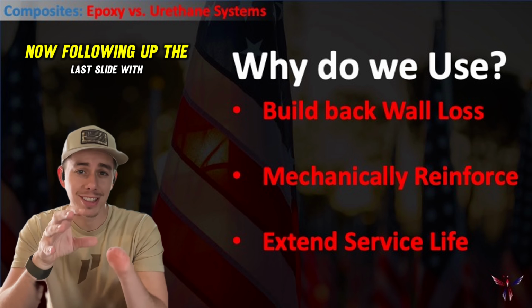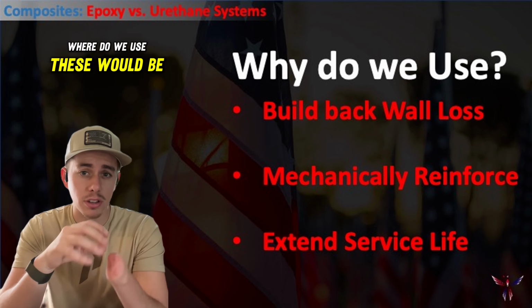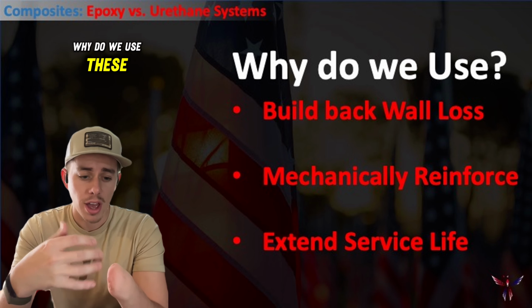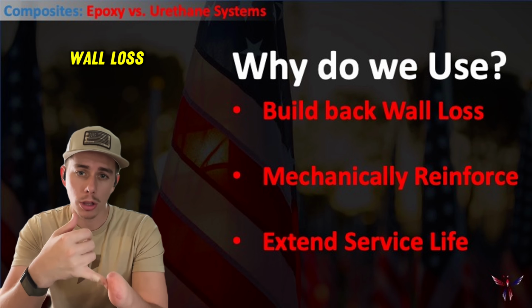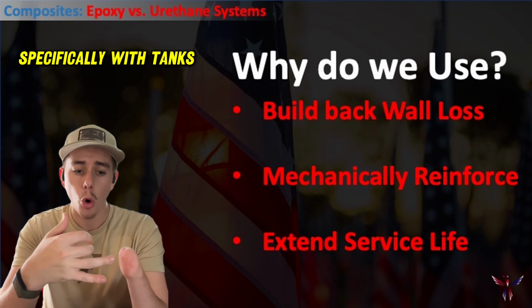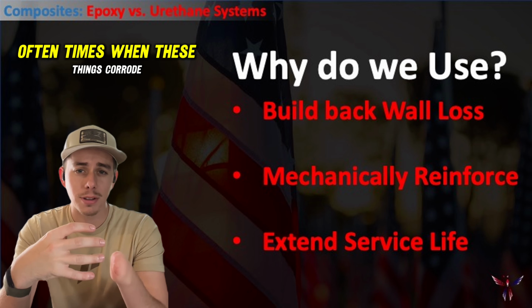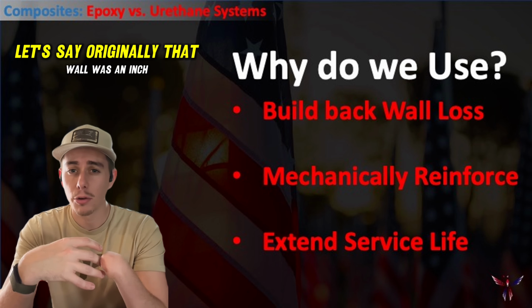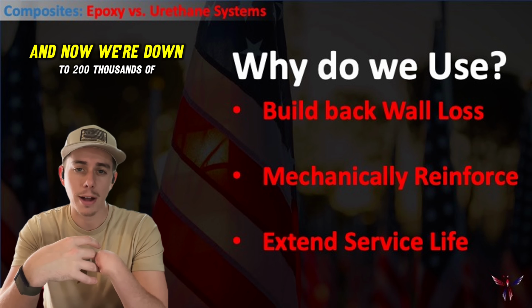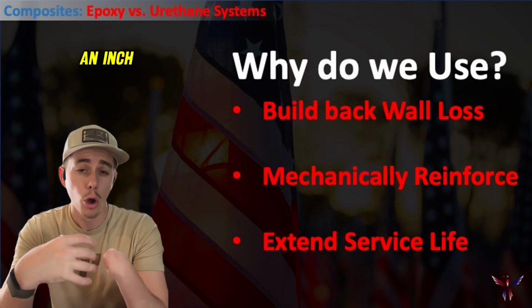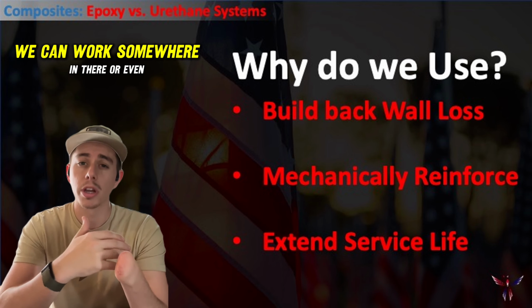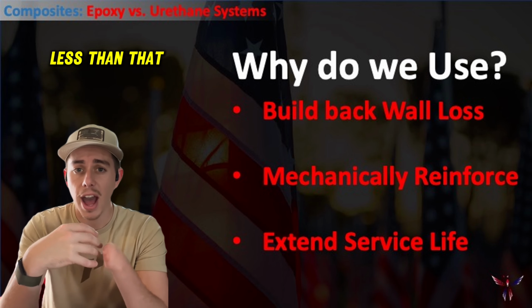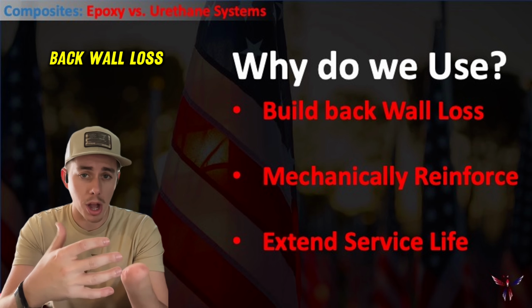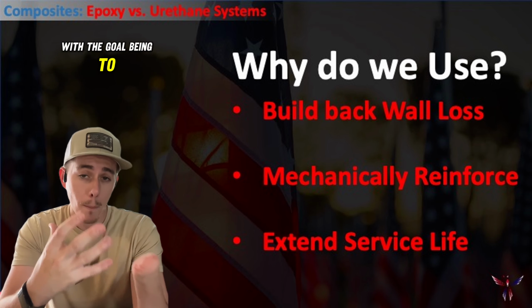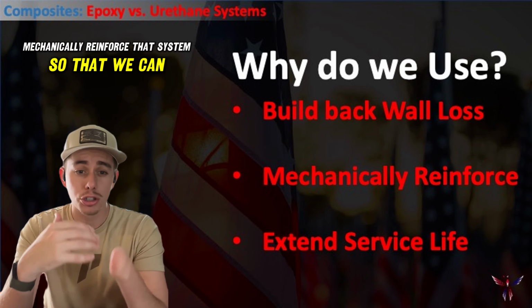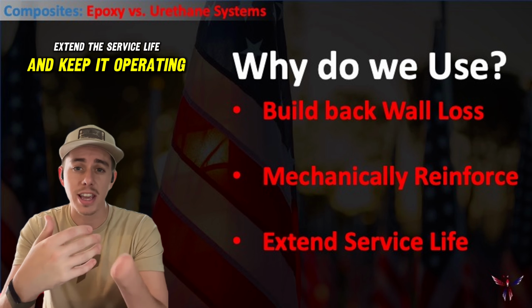Now, following up the last slide with where do we use these would be why do we use these. And the first one is to build back wall loss, specifically with tanks or with piping systems. Oftentimes when these things corrode, let's say originally that wall was an inch and now we're down to 200 thousandths of an inch, which would be about 80% wall loss. Now we can work somewhere in there or even less than that, but what we're trying to do is build back wall loss, with the goal being to mechanically reinforce that system so that we can extend the service life and keep it operating.